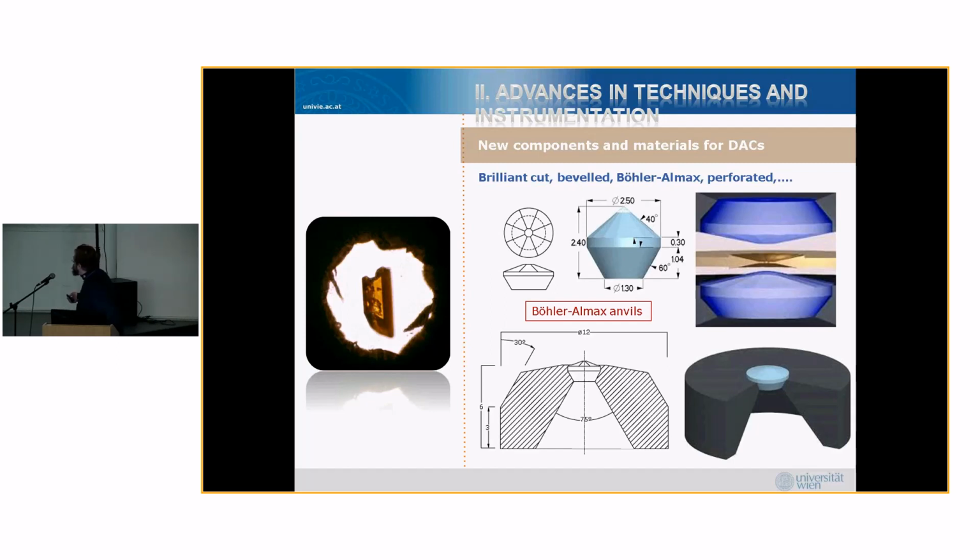And so you do the same here, basically. You use the diamonds with these conical faces to sit on the support underneath. And in this way, you can really get a better compaction even of your anvil, and the deformation is a little bit more reduced. So it is a good development that has been extensively used in the past few years, routinely, for going to these multi-megabar pressures.